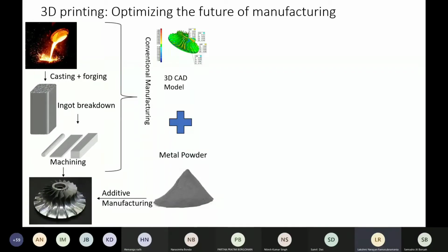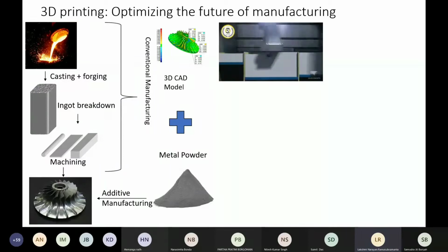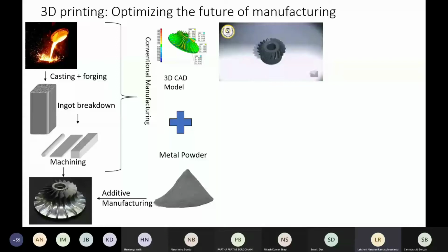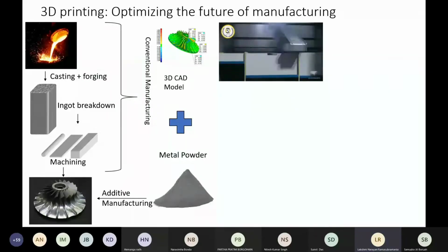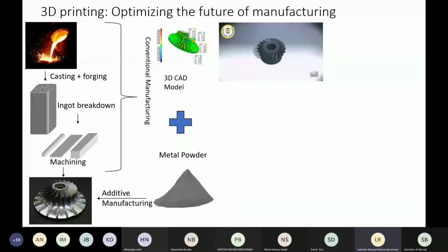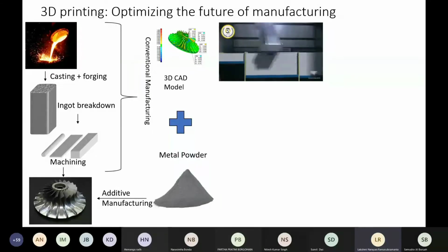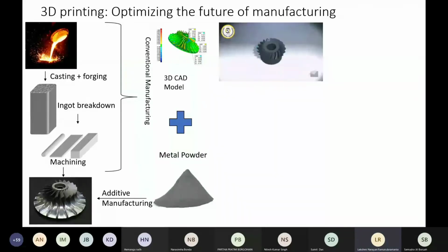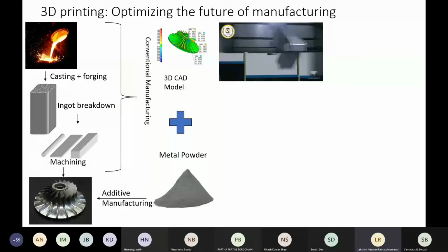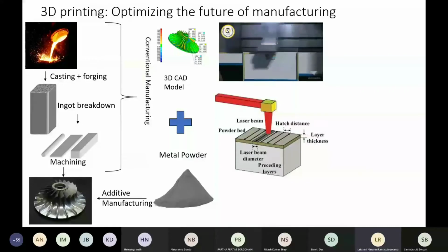And how does this happen? So this seems like magic, obviously. But what happens is you have a retracting powder bed wherein you have given the instruction to the computer that the laser should run over a certain pattern. And once that pattern has been melted by the laser or the electron beam, the bed retracts downwards and then another layer of powder is deposited over the same bed. So it is nothing but layer by layer, piece by piece reconstruction of the material which has been fed into it. And it is done by either melting or sintering the powders using a laser beam or an electron beam. And this is how the process looks.